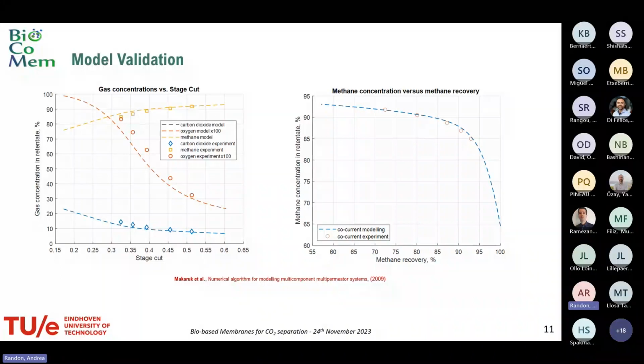We validated also the model with the experimental data. You can see in the two figures, the experimental data are the dots, while the dashed lines represent what the model calculates. And if you see in the figure on the left, the model values are in good agreement with the measured values, except that they slightly overestimate the methane enrichment.